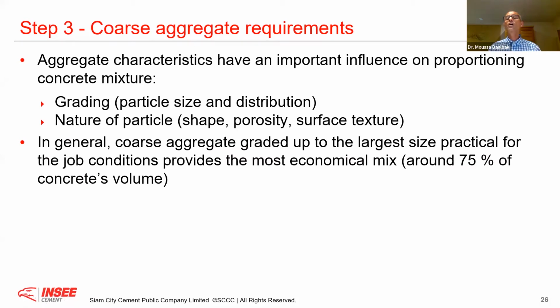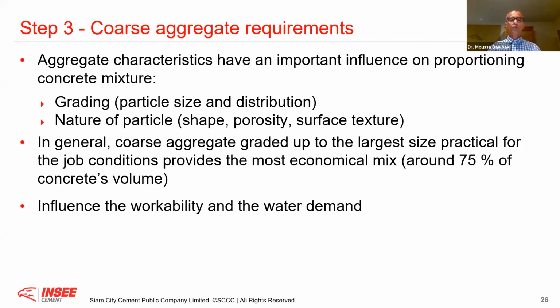That is a lot. Therefore, it's very important that you optimize your concrete mix design if you want, for example, to reduce shrinkage cracking. First thing, you optimize your aggregate content in your concrete, because the aggregate will never shrink. Okay, this is the anti-shrinking component in your concrete. But if you reduce your aggregate, you increase the volume of paste, the concrete will shrink. And also, the coarse aggregate has an influence on the workability and the water demand. So you have to find out the optimum. We will see what is the optimum.